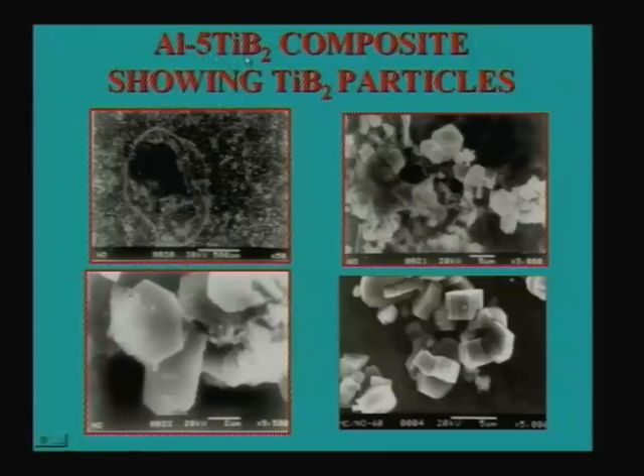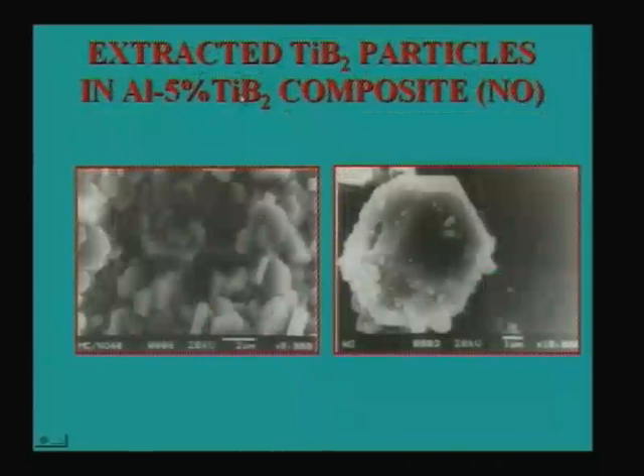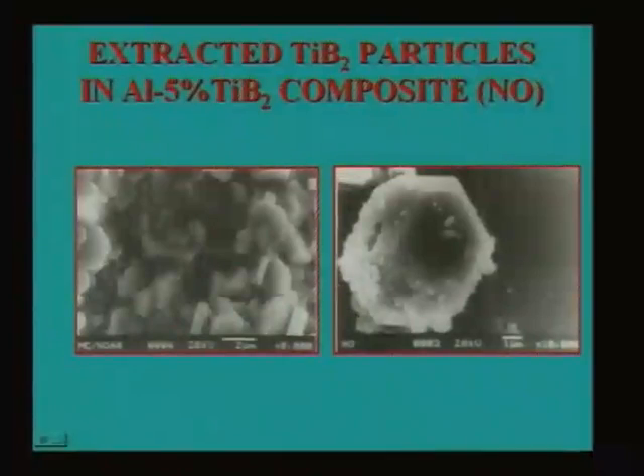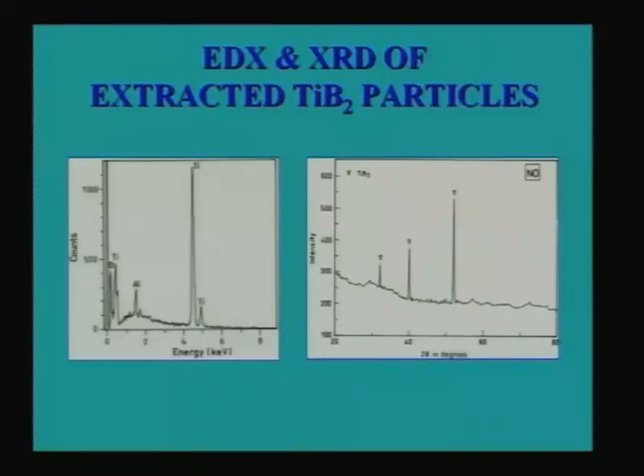This is for 5% TiB2, we will also come to 10% TiB2 a little later, and this is the extraction of particles we have talked about. That means one can dissolve all the aluminum matrix and show the three-dimensional morphology of these TiB2 particles. Once the whole aluminum has been dissolved, you have these powder particles of TiB2 which you can see under the SEM, and one can also take them to X-ray diffraction and confirm that it has only TiB2 and nothing else.